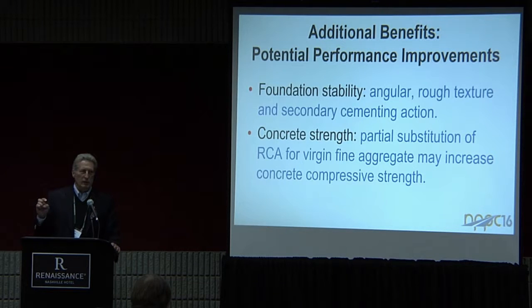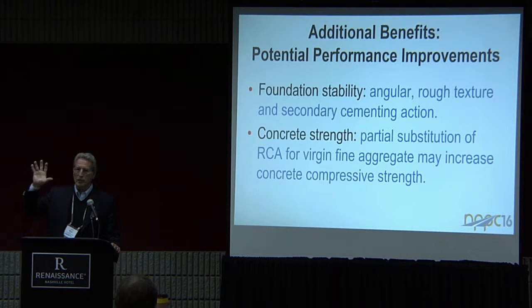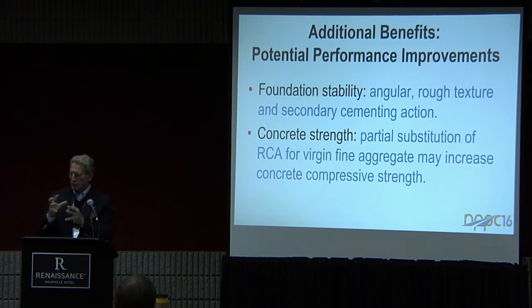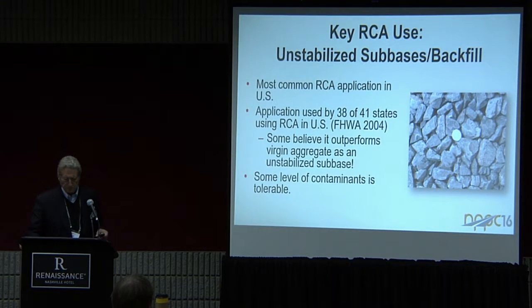A little higher compressive strength of the concrete results. Maybe partially it's a different size material. It fills in a gap in the gradation that we don't normally see when we're using natural sands and natural coarse aggregate. The recycled material fills in a gap there, which gives us a little denser packing maybe of the aggregate particles. Not sure really what the mechanism is, but it's a genuine effect.